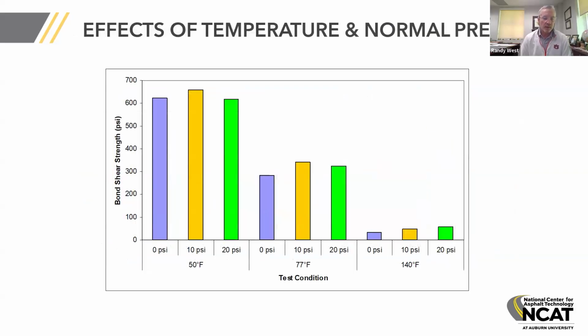One of the things I want to point out is the effect of temperature. Obviously, with asphalt binder, we're talking about a viscoelastic material. So as the temperature goes up, its strength or stiffness or shear resistance is going to go down, and that's very obvious in this shear test. At 140 degrees, you see really low bond strengths, and that's probably the critical condition in the field, when you have pavements that are very hot in the summertime, and they're going to have the lowest shear strength.